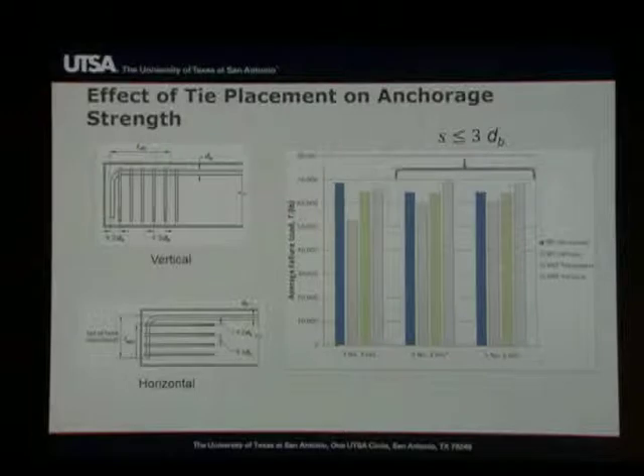And in the 180-degree hooks, you tend to see somewhat of a similar effect. The 180-degree hook would come back here, and so the bars that would restrain the tail end of the hook would be the vertical bars, and you will see here that 180-degree vertical did a little bit better than 180-degree horizontal. But all in all, if you abide by this limit of 3 bar diameters, the effect of placing the transverse reinforcement in one orientation or the other is not significant for either orientation of the hooks.